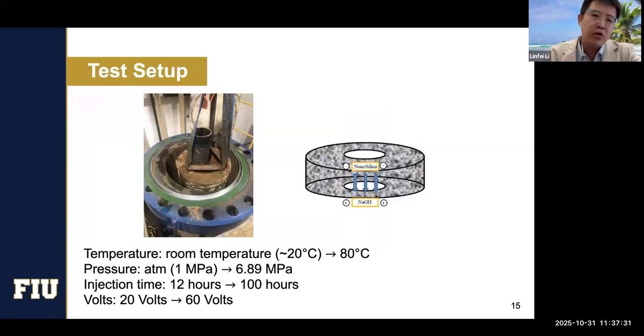For the test setup, we set up a steel casing, which is exactly the same size as the underground project. We put that in the middle, and then we cast the cement between the concrete surrounding and the steel casing. Later on, we took it out and ran the injection. We set up two reservoirs, as we did for the small scale: one side is sodium hydroxide, the other is nanosilica. We figured out nanosilica might be one of the most promising ones, so we took nanosilica as one, but we also tested other different types.